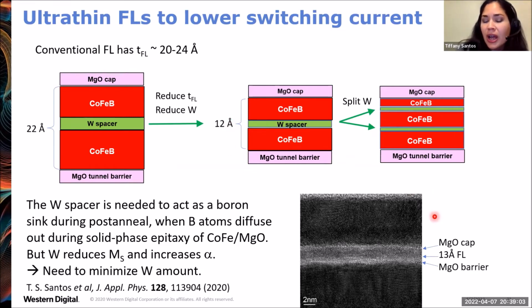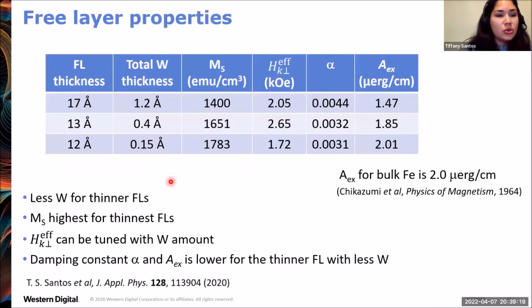So I'm showing here a TEM cross-section of, for example, a 13 angstrom cobalt iron boron free layer with the MgO barrier at the bottom and the MgO cap at the top. We proceeded to do this free layer design for a ladder of free layer thicknesses. So 17 angstroms was the thickest one, then 13 angstroms, down to 12 angstroms. And by reducing the free layer thickness, we're able to substantially reduce the tungsten spacer thickness. This resulted in a lot higher saturation magnetization, a reduction in the damping parameter, and also an increase in the exchange stiffness, reaching values that we know for bulk iron, even for these cobalt iron boron free layers that are very thin.